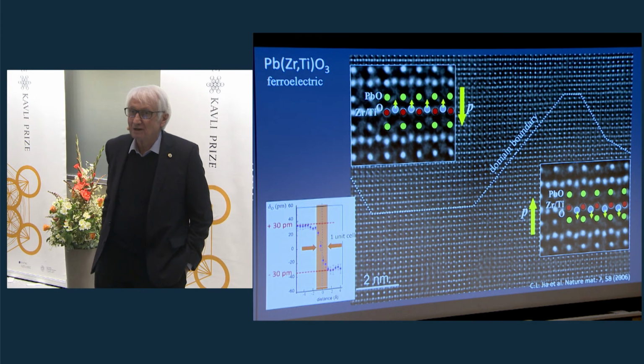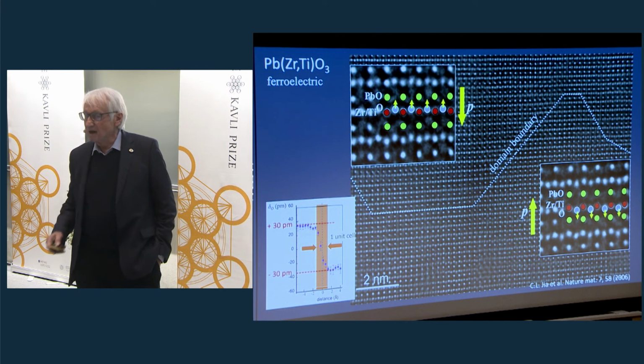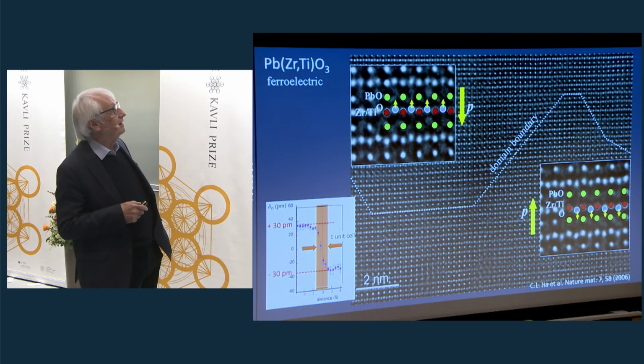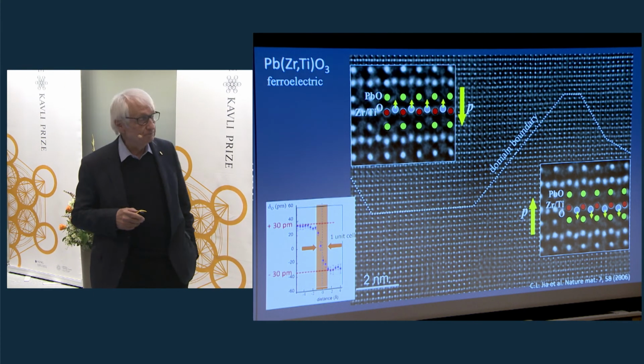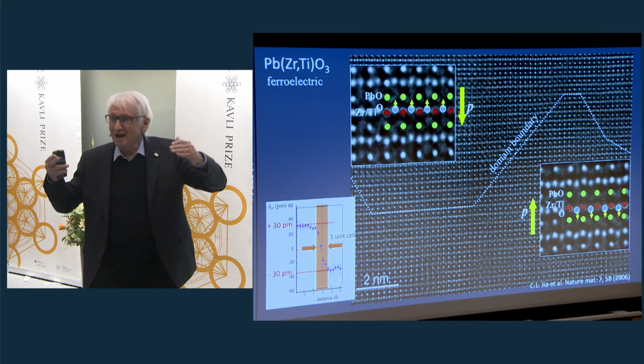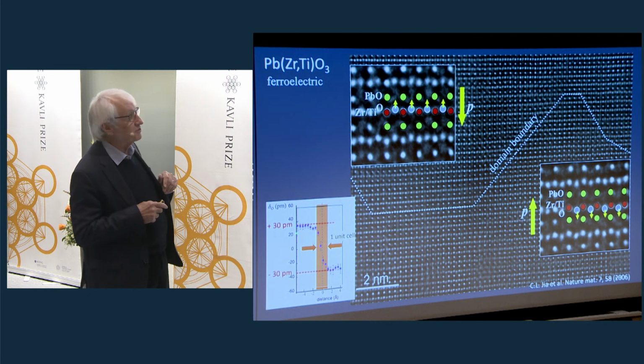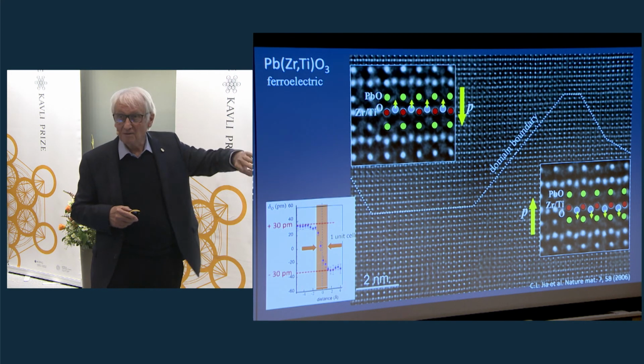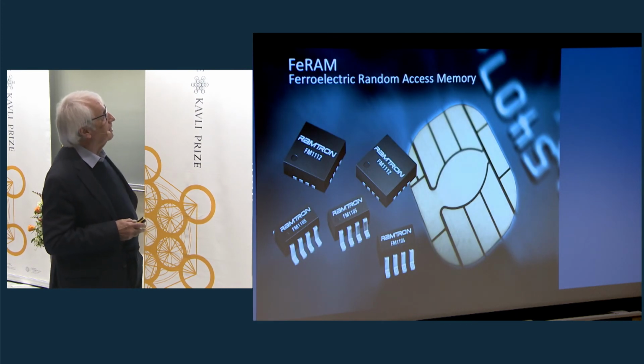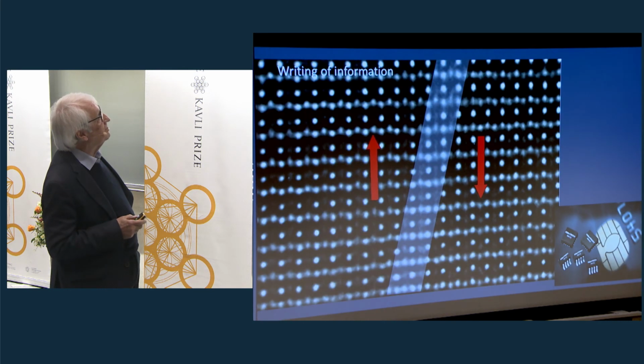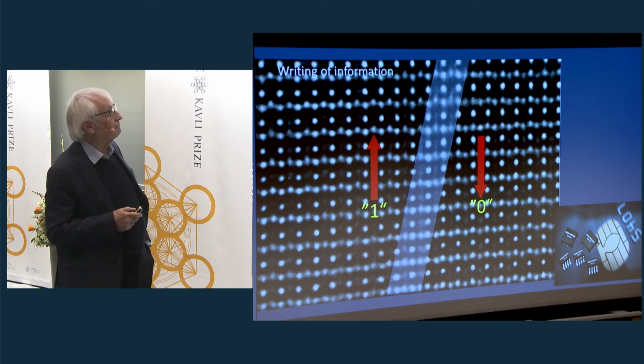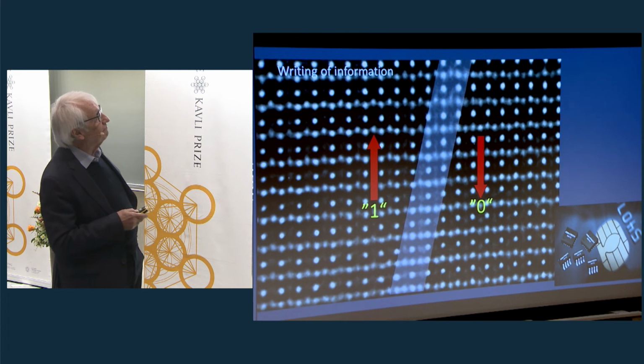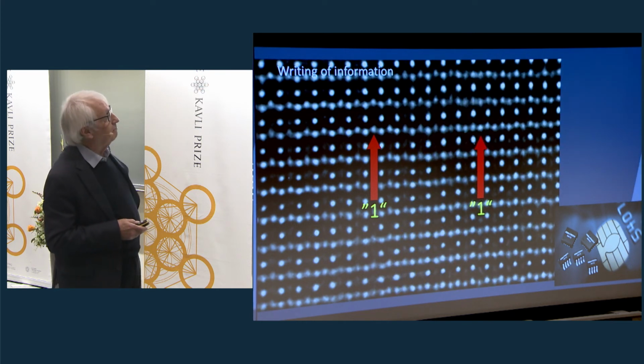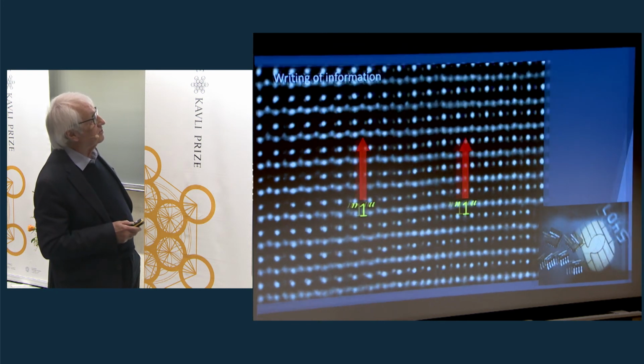When you have chip cards in your pocket, bank cards and others, some of them store information in the form of such polarization patterns. That means an everyday life function is based on shifts of oxygen atoms 30 picometers up or 30 picometers down. These are the ferroelectric random access memories. So we just here take oxygen up as a binary 1, and oxygen down should be a binary 0. Now we apply an electric field. The domain wall shifts, and we inscribe in this way a binary 1 to the other side.